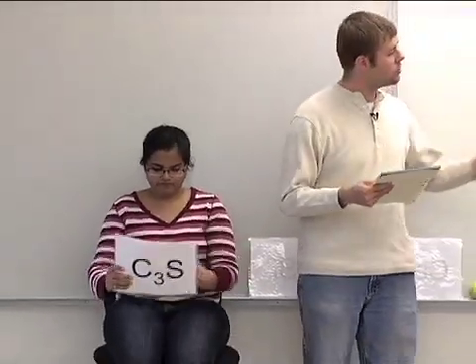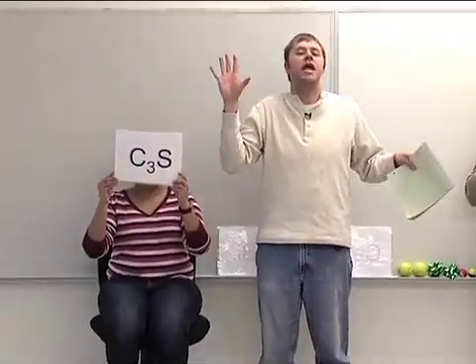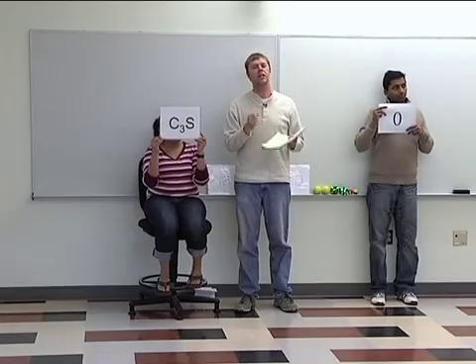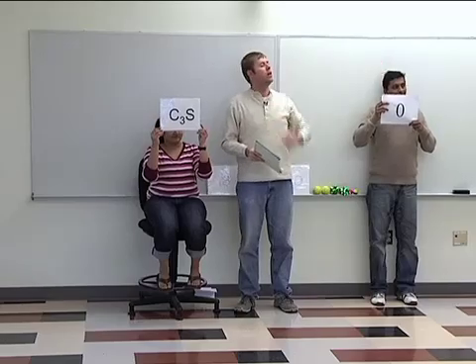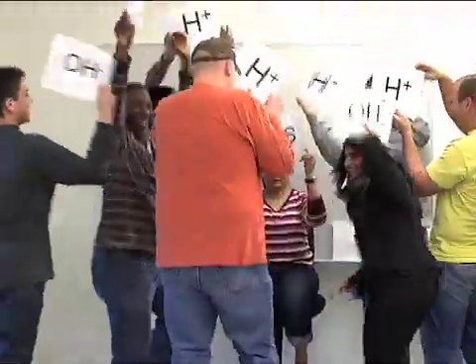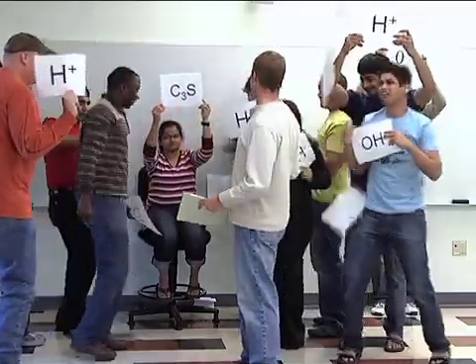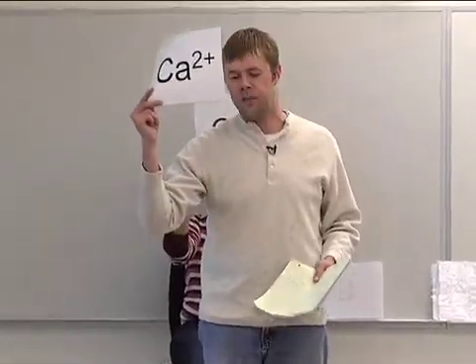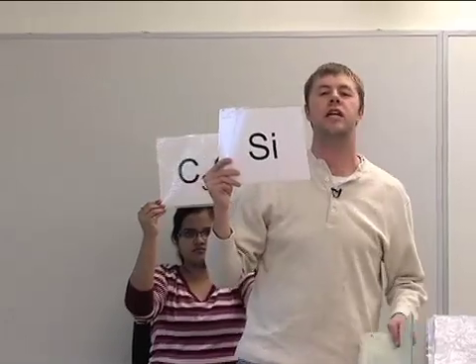We have our cement grain, our scale, and we're at time zero. Then all of a sudden, the very first step in hydration is mixing — you get the water, add it to the cement, and start mixing it up. Water molecules come in and tear at the cement grain, freeing calcium ions and silica ions, sending them flying off into solution. The levels are getting higher and higher — we're at picoseconds now; this isn't even a true second. This is hydrolysis — what happens very early on.